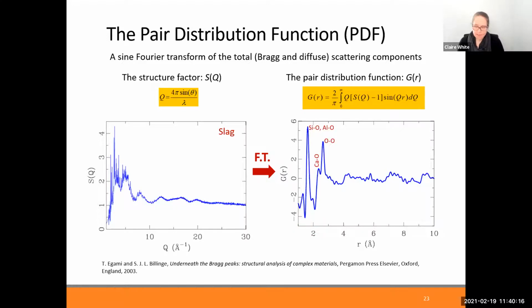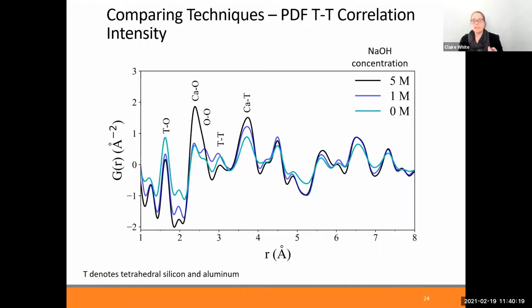And so we did this analysis for the synthetic gels. Here are the pair distribution functions for the same gels I showed you previously with the NMR. What we see here is tetrahedral silicon or aluminium, with a bond length at about 1.65 angstroms. There's calcium in the system, especially here, where the calcium actually goes up when we're at the high sodium amounts. So there's quite a lot of calcium in this system, less in the other ones. And then we have atom-atom distances. This is silicon-silicon, silicon-aluminium, aluminium-aluminium distances. This is calcium-silicon, calcium-aluminium distances, and you keep on going.